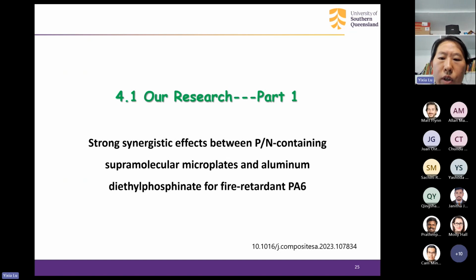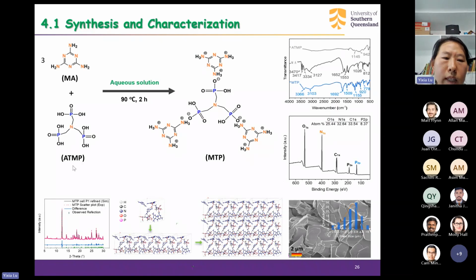This research is published on the Journal of Composite Part A. In this research, we use melamine and ATMP as the starting materials with a molar ratio of 3:1 to synthesize MTP. And we also characterized the product. As we can see, it is a microplate appearance by using SEM. And we also investigate the chemical composition and microstructure.